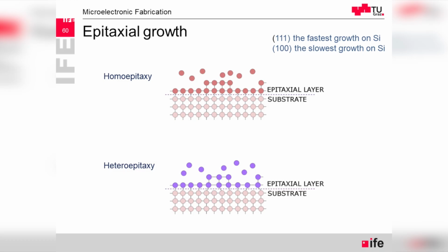And then with the introduced gas, we have atoms of a different material, also semiconductor, or the same semiconductor silicon, so homoepitaxy or heteroepitaxy, which in high temperature, when the process is in high temperature, then the atoms will continue aligning following the crystal structure.